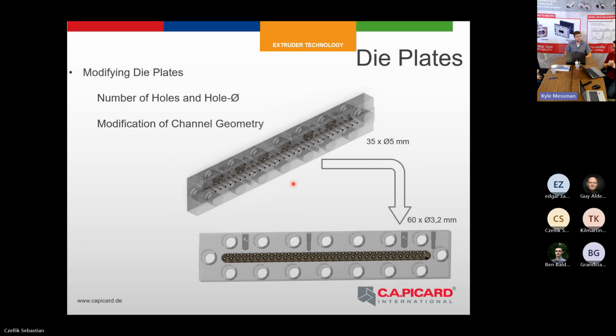Some customers are using the die plates as the last part in the extrusion process, and some customers are asking us to modify this, especially regarding the number of holes. In this case, we transformed this die plate from 35 holes with 5 millimeter diameter to 60 holes with 3.2 millimeters.